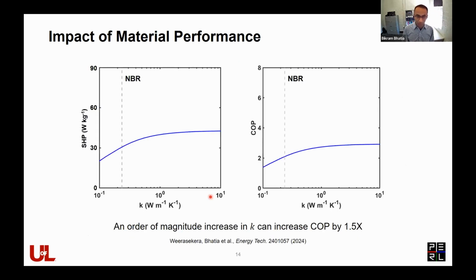for different material systems. So we used this model and looked at the effect of different material properties on the device level specific heating power and COP. One representative result that I show here is the SHP for nitrile butadiene rubber as a function of thermal conductivity. As you would expect, as thermal conductivity increases, the specific heating power as well as the COP increase, while all the other properties are held constant for an imaginary device. So we have this model that we can now use to correlate all the material properties to actual device